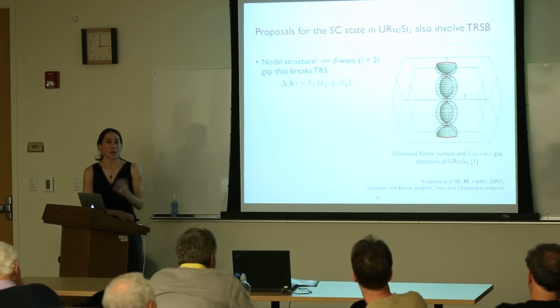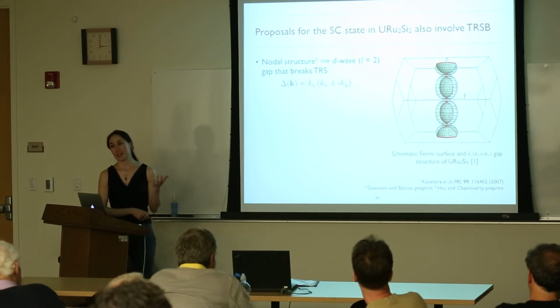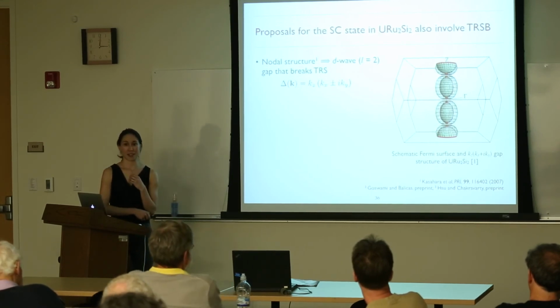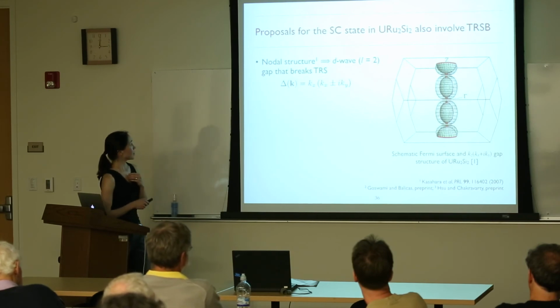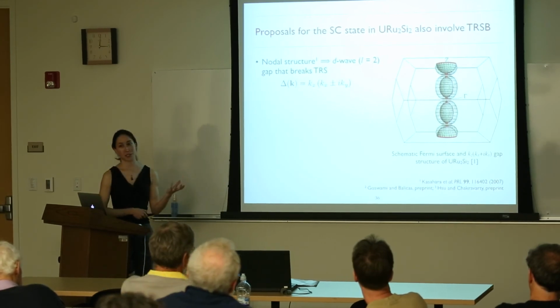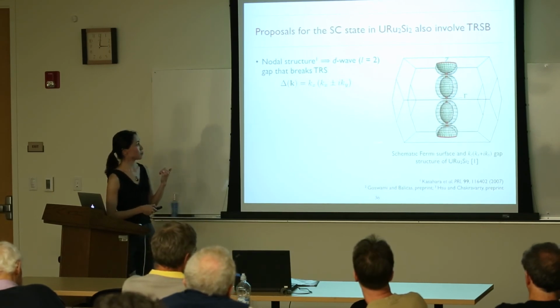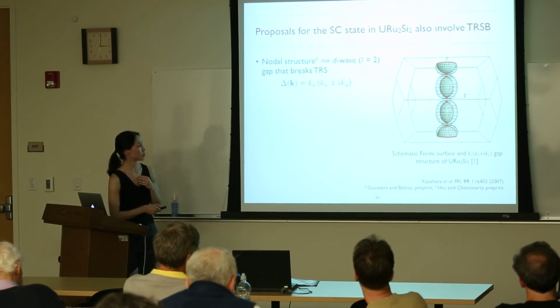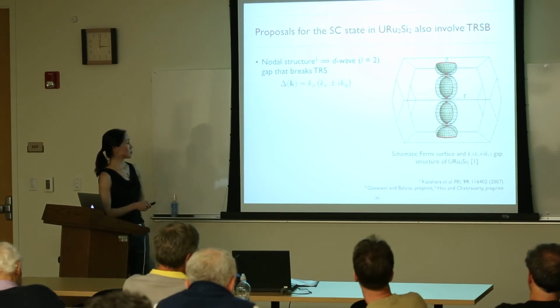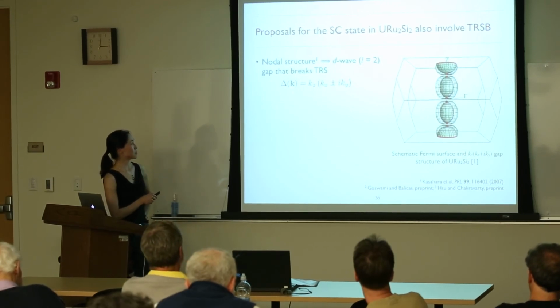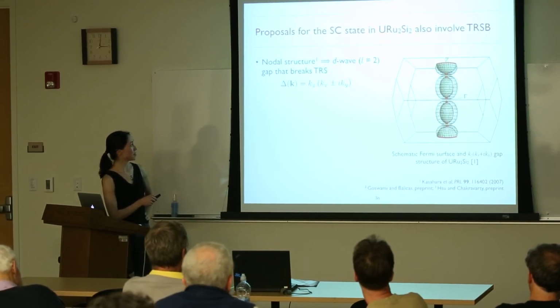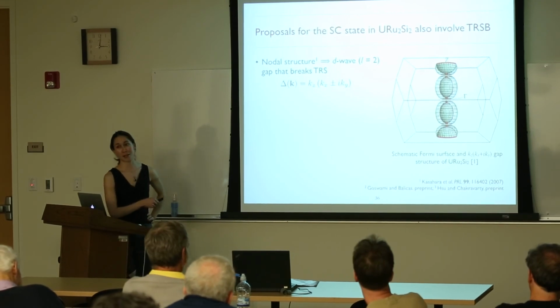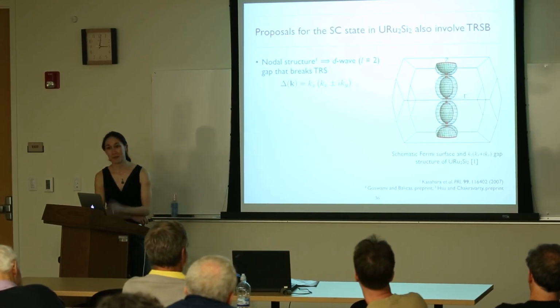Okay, so my particular reason for being interested in this material, despite the fact that it has this very confounding high temperature phase, is the fact that there's at least some work that suggests that time reversal symmetry should be broken in uranium ruthenium-2 silicon-2. The work on the nodal structure has led to a sort of cartoon picture of the gap that's like this. It has point lobes and the like. So this at least would be consistent with some interpretation where the gap is so-called d-wave, so L equals 2 for those of you who like that. Anyway, it's kz(kx ± iky), which, as you may recognize by now, is something that should break time reversal.